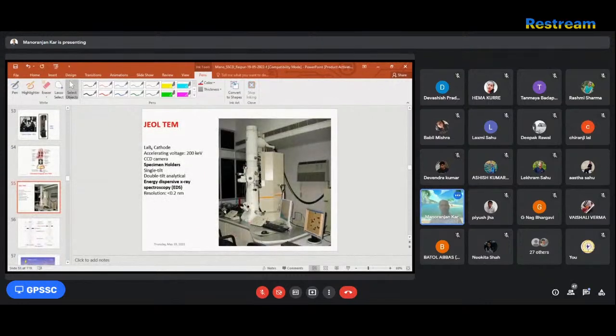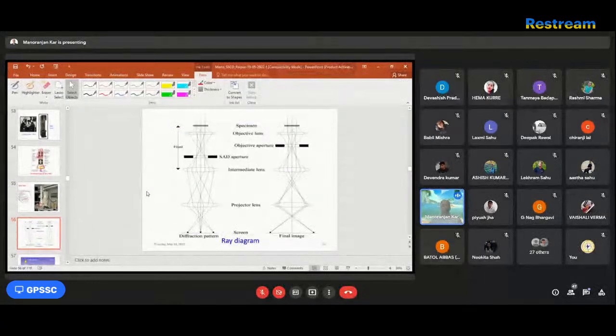And if you look into the micrograph, this is the TEM, and you see that it is the column, electrons are going, and finally there is the camera here. If you go anywhere, you'll find that. The concept and machine, more or less for all the companies, fall like that. These are the specifications for this. It is 200 kV, but it is a thermionic emission gun, and we call it the dirty electron. Its resolution is a little less, but it is good enough to look at atomic resolution, or lattice and so on. If you look, these are the ray diagrams.